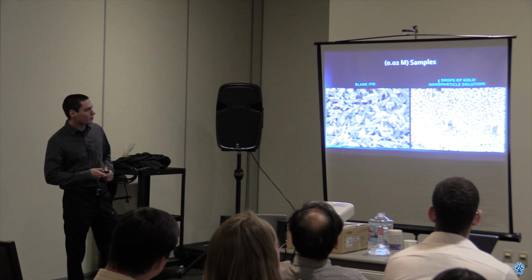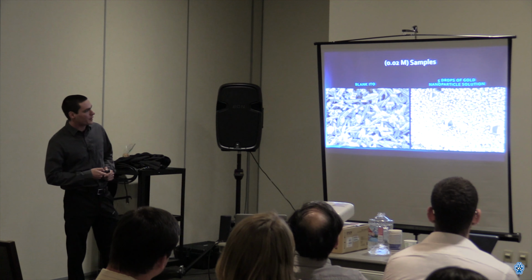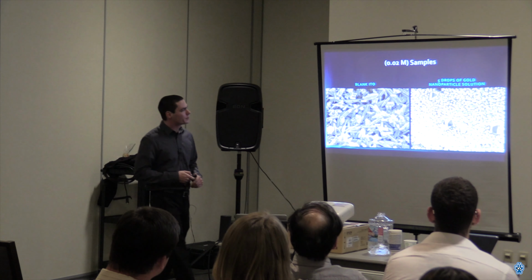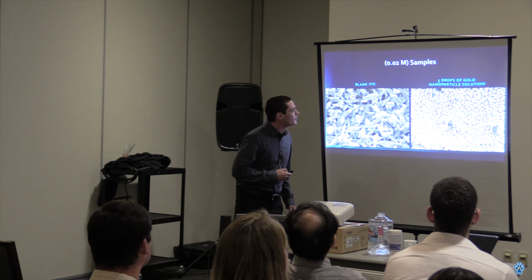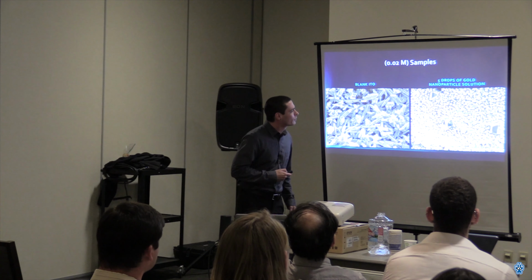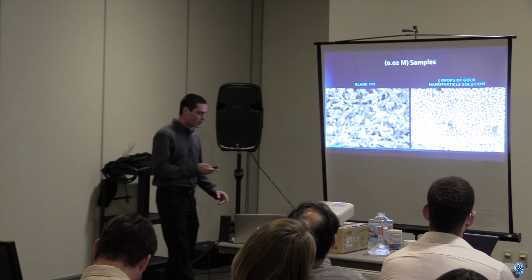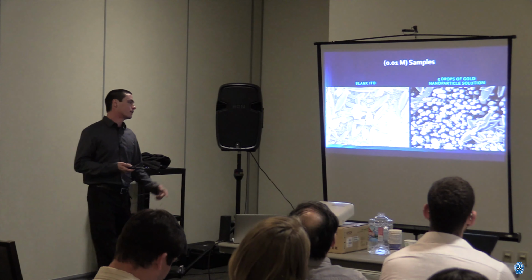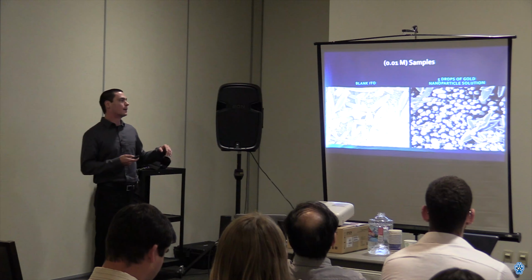I mean, they have similar structures, so this rod is analogous to this one here, but you could imagine that underneath this cluster here is almost little pebbles, and their dimensions are much, much finer. I even have to get close to read it, but this one is 0.87 micrometers, 0.74, 1.14. So overall, they're much finer resolution than the original. And here, the only difference, again, was the concentration of the solution.